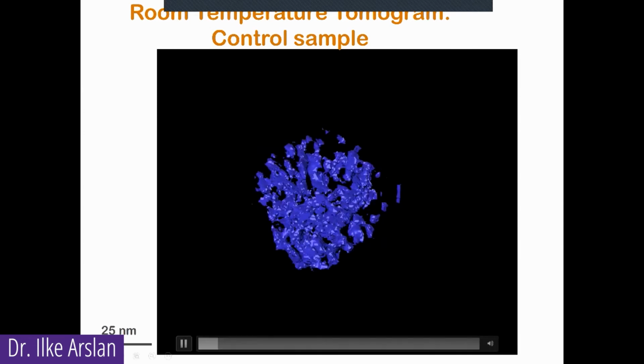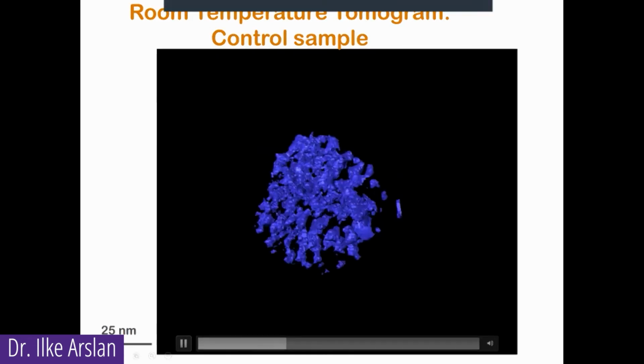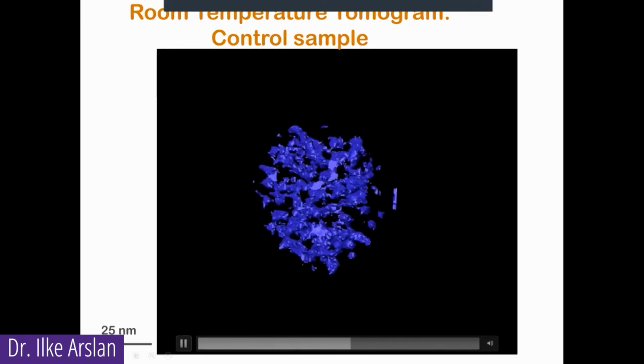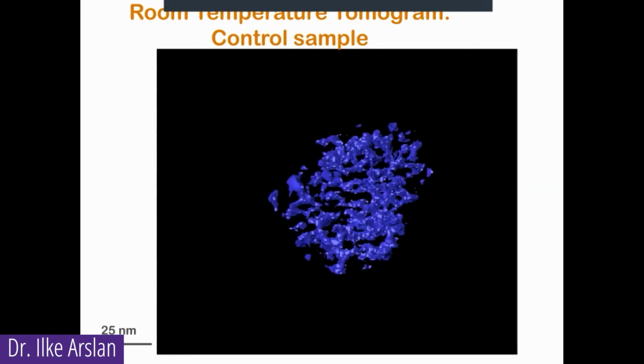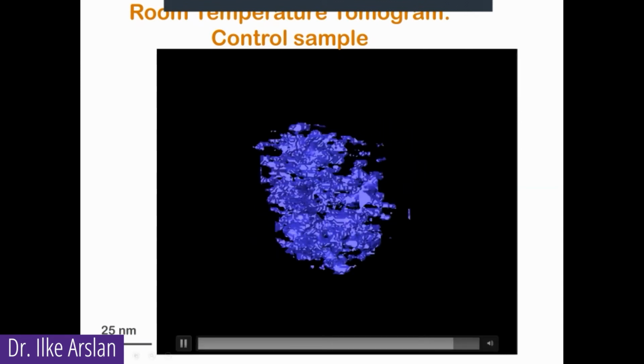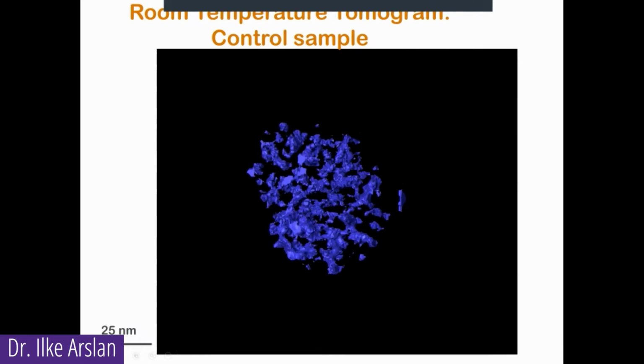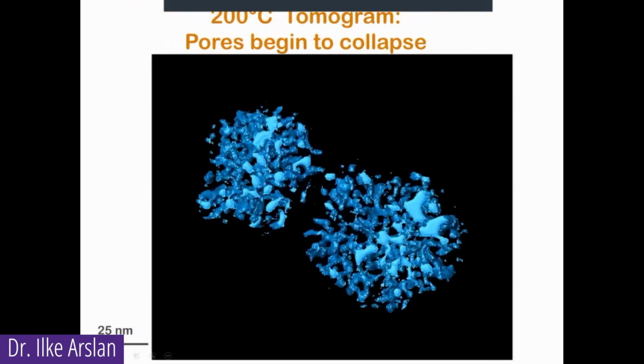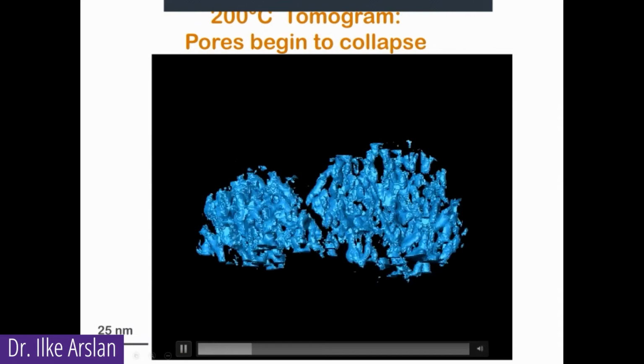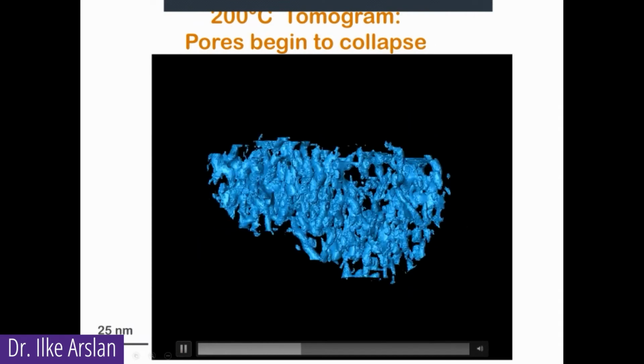Other than the slight elongation that you will see if you're used to looking at tomography data, you can see that the pores are pretty uniform and they're about 3 nanometers in diameter. When we looked at the pore structure, again, this is the inverse. What you're seeing in blue is only the pore structure, and ignore these surface effects from the reconstruction. But if you look inside, you can see that it doesn't look quite so uniform anymore.